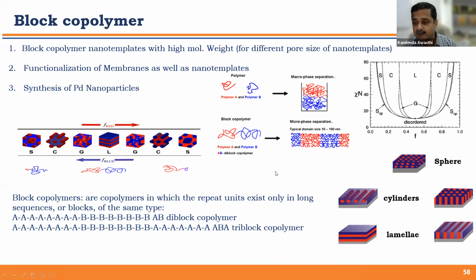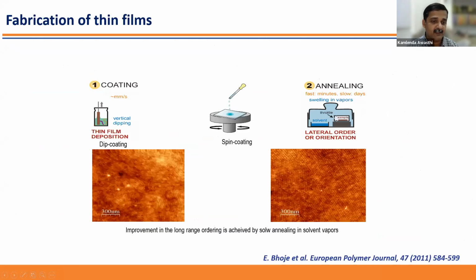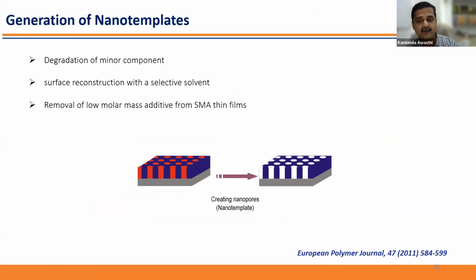These are the various morphologies that are possible in block copolymer membranes, but particularly if we are interested in filtration, cylinders that are perpendicular to the surface may be our interest. Here we do not need any kind of ion beam or other treatment to make them porous. We are using this PS-P4VP polystyrene-based membrane. Simply by using spin coating, then solvent annealing, what happens is that the other component of the polymer can be washed out.